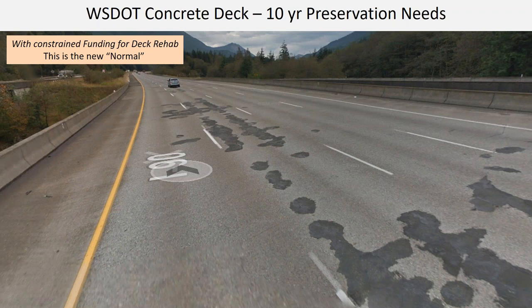You'll see crews, and the black material is a urethane-based patching material that the crews like because they can mix it, add a wand, and then they can get traffic back on in a short amount of time. This material cures out in about 20, 30 minutes.